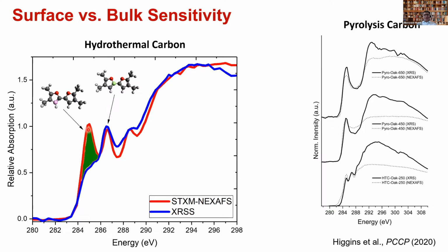And this is not only limited to hydrothermal carbon. Also in pyrolysis carbon, when we used the exact same material to do our NEXAFS versus XRS studies, we found that there are systematic changes as a function of temperature. Here's 650 versus 450, and here is HTC material at 250, for example. So again, what these differences tell us is how we can use these materials for designing desired properties and tailored applications.